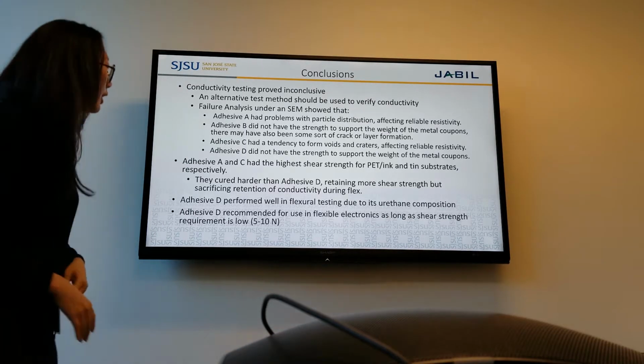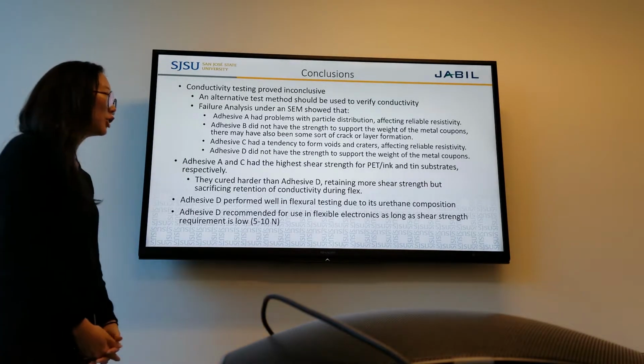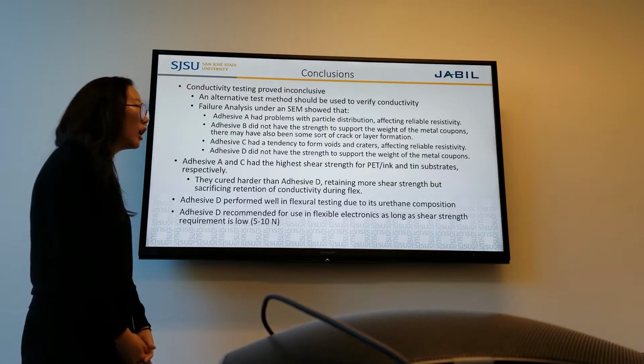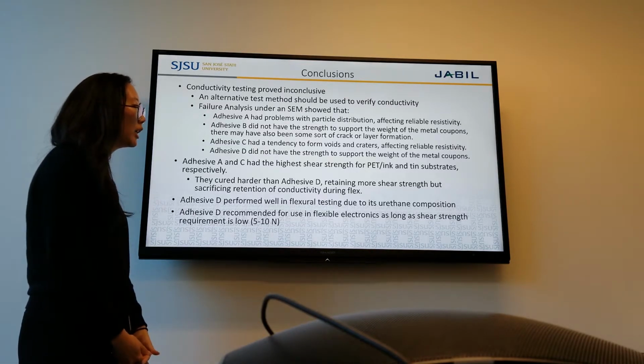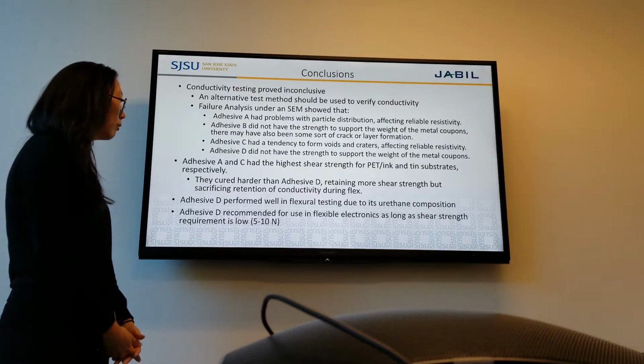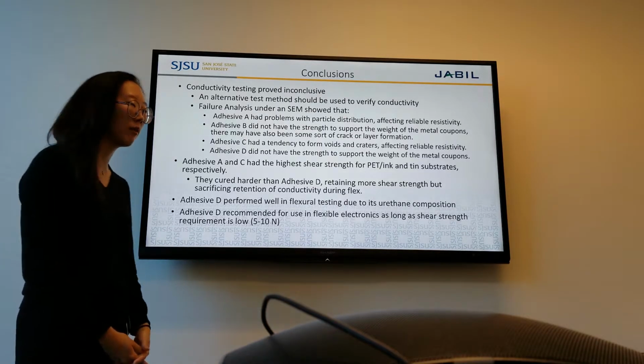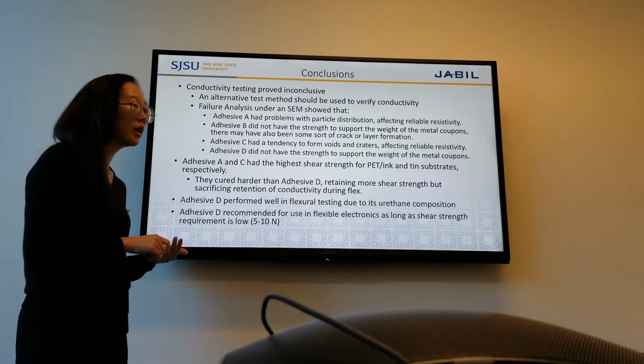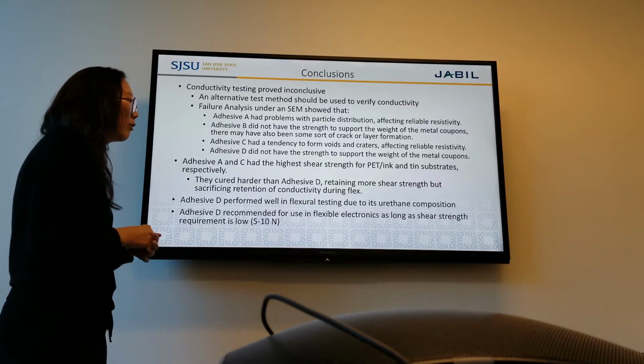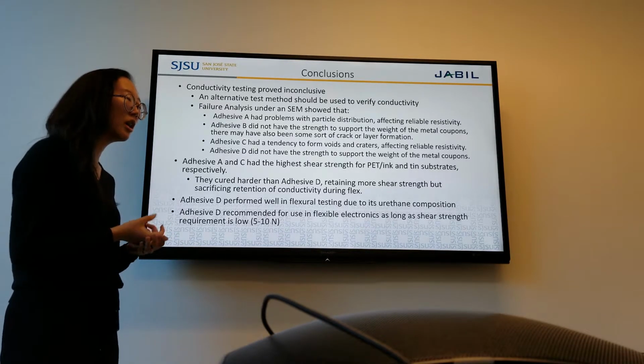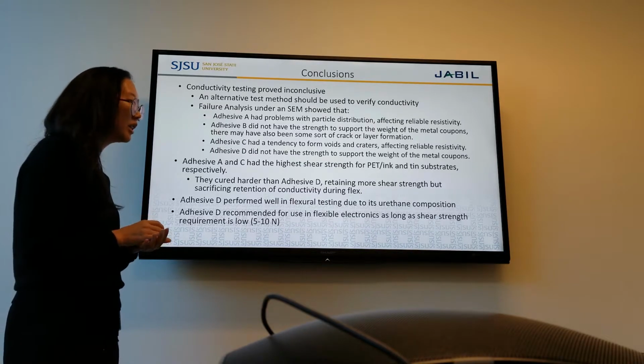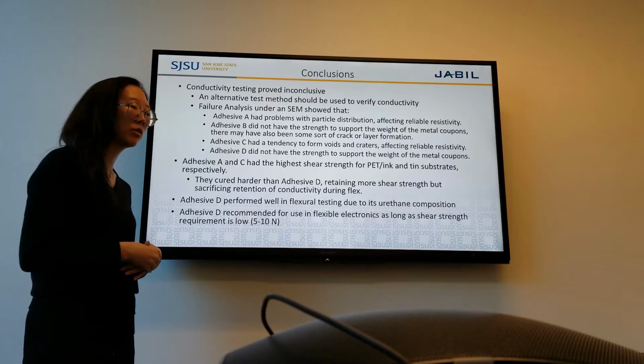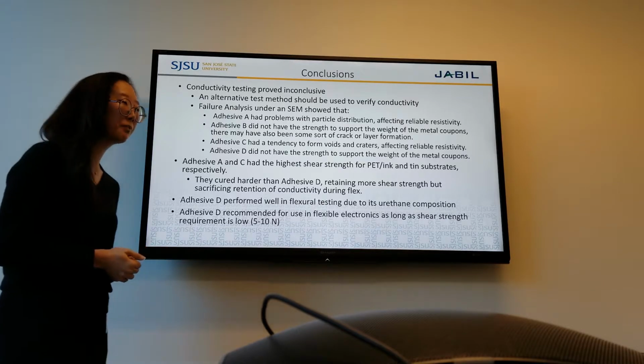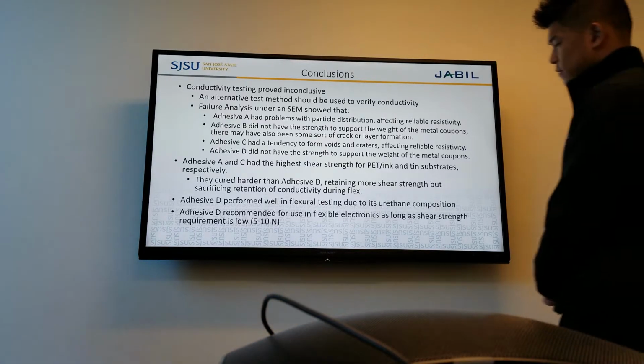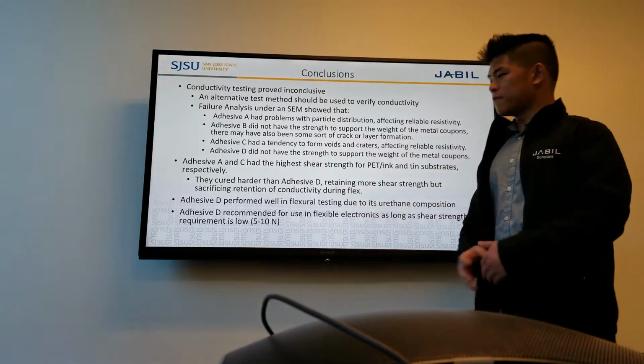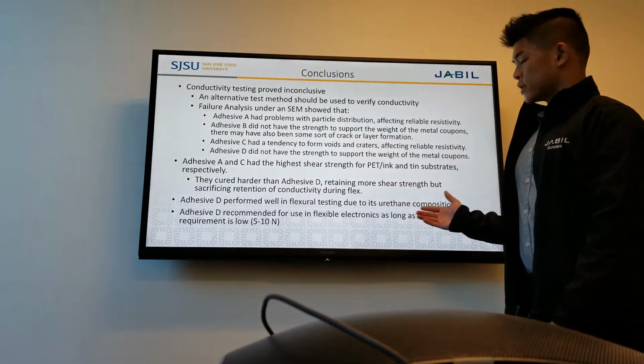And for shear strength, Adhesive A and C both showed the highest shear strength for both PET and ink substrate and tin substrate. However, when it comes to the flexural test, they failed due to how hard the adhesives become when they are cured. Adhesive D, when it's cured, is not as hard as Adhesive A and C, so during the flex testing, it's able to perform pretty well. In our flex testing, Adhesive D performs very well due to its urethane composition.